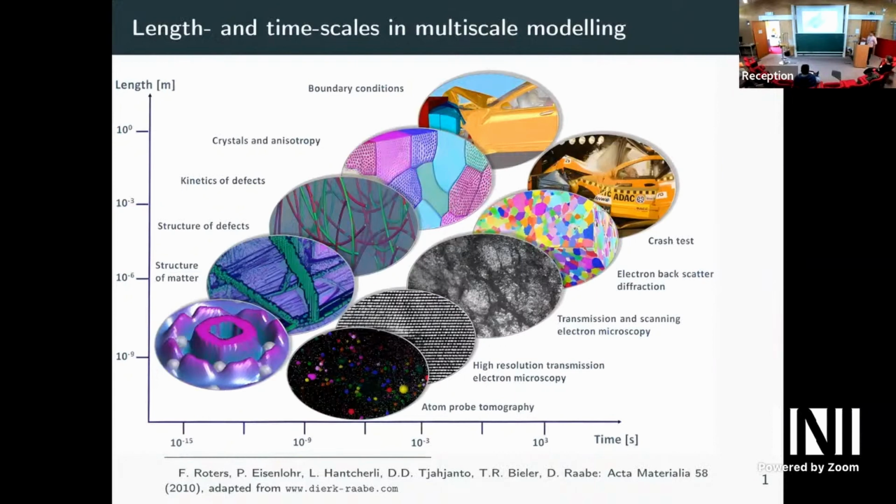You can also jump further to polycrystalline materials. Then you have crystalline structure with different orientation, and at the boundaries, you typically have an awful lot of these dislocations that try to correct for the misalignment of atoms. And then you can coarse grain even further, and ultimately you reach the macro scale, the finite element scale, the continuum scale, where, for instance, you do homogenization at this stage to get some effective material properties that you can then pass on to finite element simulations.